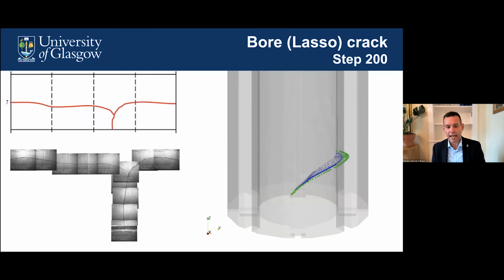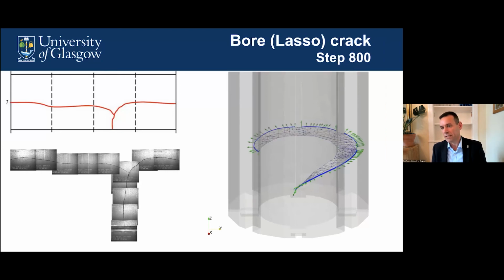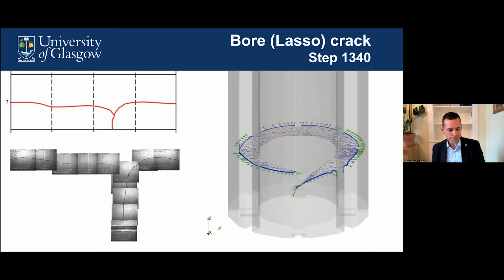And if we look at some snapshots of that and compare it to what's observed during inspections, on the bottom left are the images from the inspection, and then on the right are our simulations at different snapshots in time. And qualitatively, we're getting pretty good agreement with what's observed in reality.